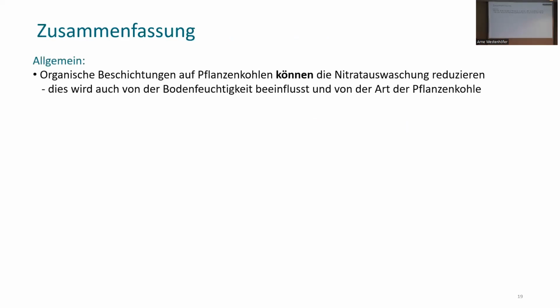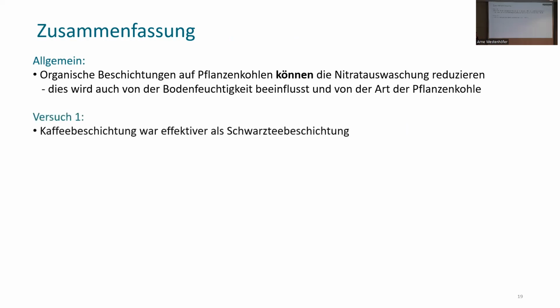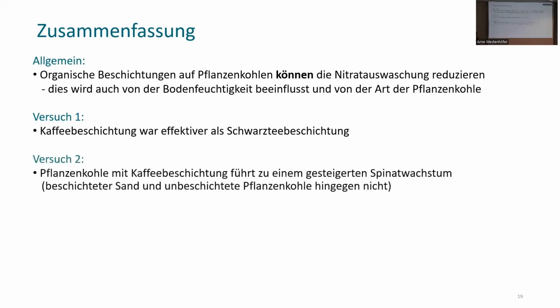Summary, we can say that the organic coatings on biochar can reduce nitrate leaching. But this is also influenced by the soil moisture and the type of biochar. Experiment one, coffee coating was more effective than black tea coating. In experiment two, the outcome was that biochar with coffee coating leads to increased spinach growth, but it doesn't work if I use only a coating and no biochar.